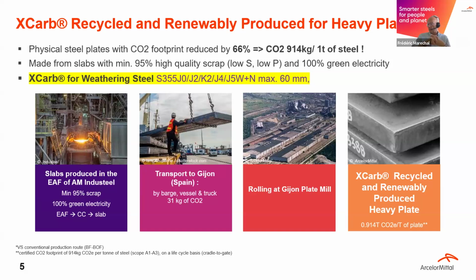And these electrical arc furnaces versus blast furnaces, they are operated with 100% of green electricity. And we feed these furnaces with almost 100% of recycled steel, so what we call scrap. So this is really recycling and nothing else. And then, these electrical arc furnaces are not exactly on the side of Gijón. We have to ship them and then to have it rolled in our mill. So at the end, with these results today of CO2 emission, we are really, for heavy plates, among the very best and the first one to propose this and for such an extended feasibility program.